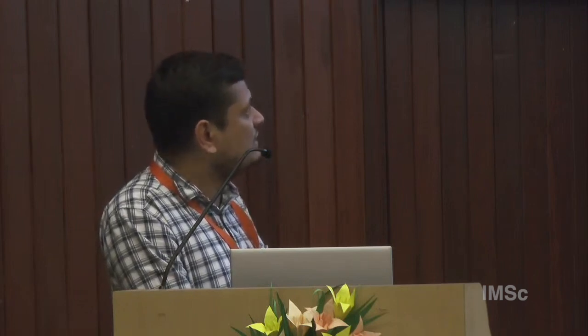What we are seeing here is that when you're doing cyclic shear and forming these cavities, the energies at which the cavities are formed under expansion are much higher than the energies that you encounter in the cyclic shear cycle. Similarly for the activity, the energies that you encounter are much smaller than the energies at which the cavitation occurs under expansion. So this suggests that the barriers to cavitation are much smaller for the secondary deformation in the expansion state. So I'll just quickly summarize what I've told.